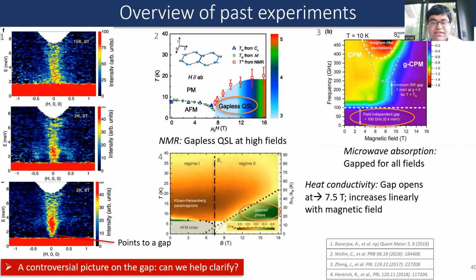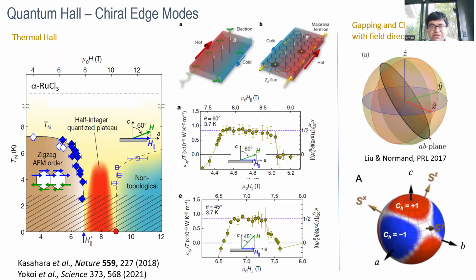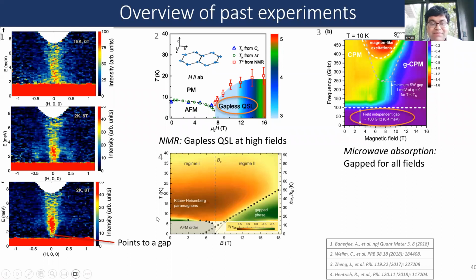In order to do these experiments, there were several groups who have several viewpoints on this, and I'm not going into the details, but one very important result came out from the group of Kasahara and Matsuda, and later the Max Planck group, who did thermal Hall measurements. They found that right at 8 Tesla, where we discovered this quantum spin liquid and gapped spectrum, you also have a half-integer quantized Hall plateau in thermal Hall measurements. They found a robust plateau phase between roughly 8 and 8.5 Tesla, which was very nice because that is more of a smoking gun signature.